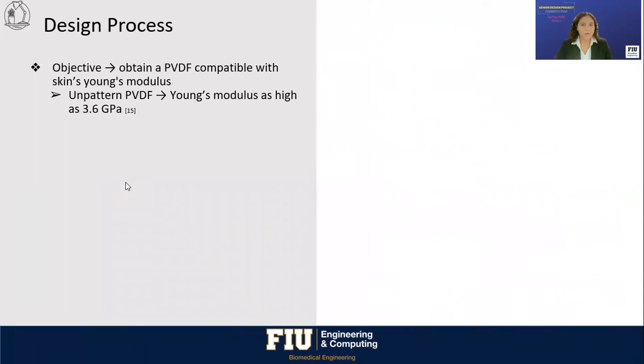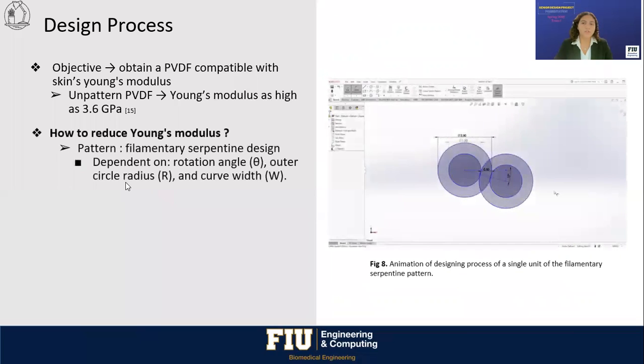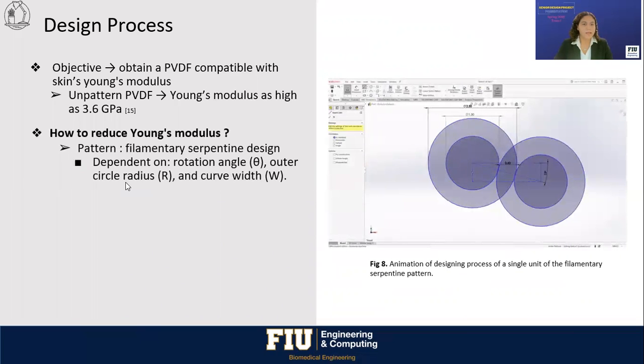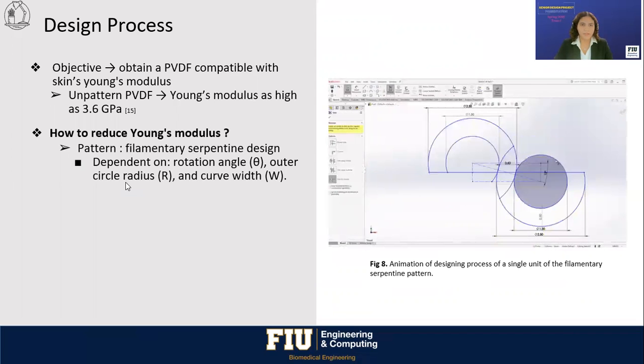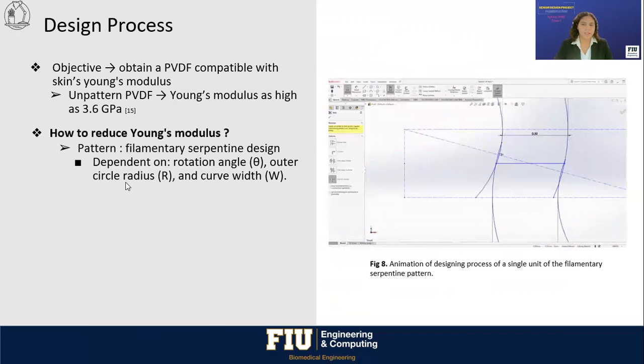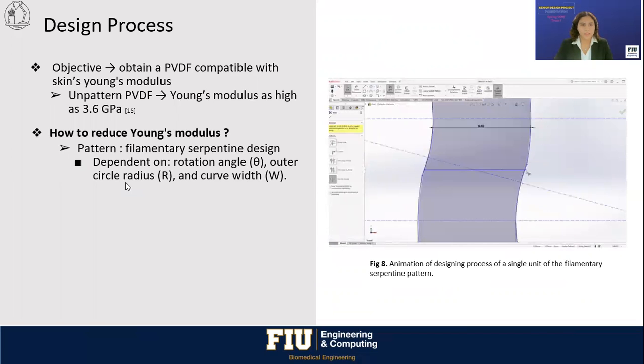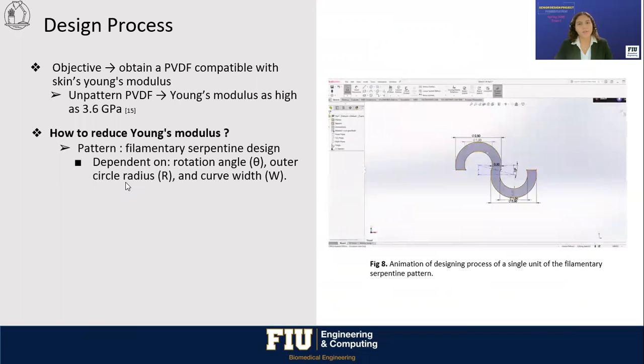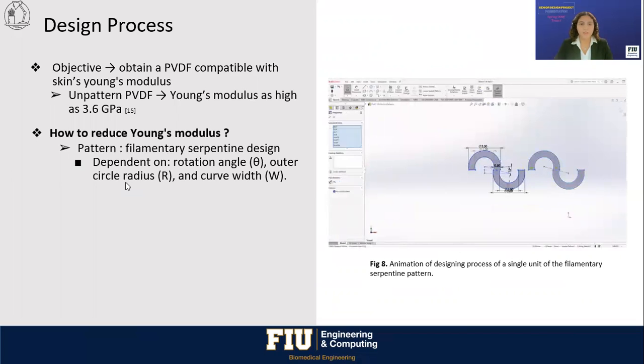Now, what do we need to pattern PVDF? Well, PVDF can have a modulus as high as 3.6 gigapascals, and our setup for skin was 20 megapascals. We can reduce its modulus by patterning it, hence where the filamentary serpentine structure comes into play. The shape depends on the stated factors, and the overall steps to making a single unit are shown on the right. It is important to note that as stretchability increases, the sensitivity of the PVDF decreases.